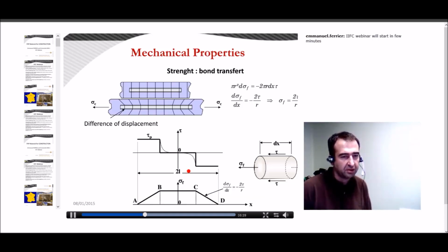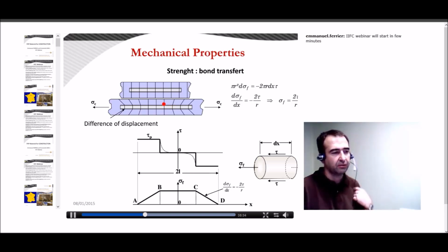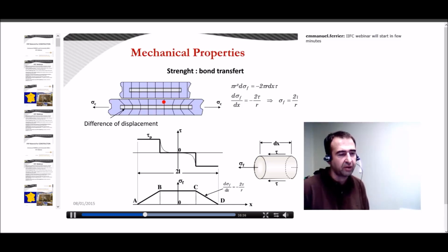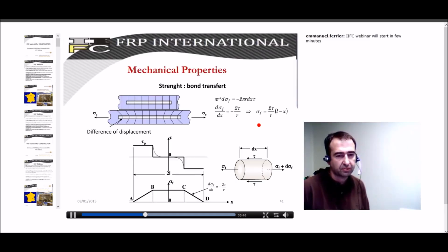Then about shear, when a fiber will be fully impregnated, then there will be a bond issue between fibers, and then there is a strength. There are strength properties to identify, which is the shear strength that can be developed around fibers to make sure that two layers will be fully bonded.